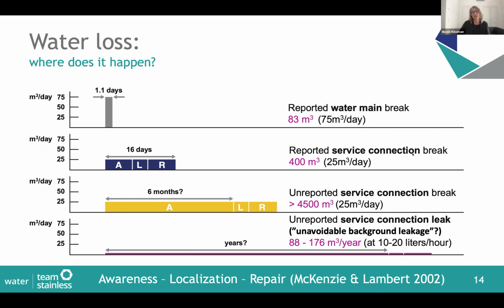But between awareness that there is a leak, and then the finding of the leak, the localization, and then the repairing of the leak, several days may pass, maybe more than 2 weeks. So during these 16 days, we can say 20 days, we can say 10 days, but we say 16 days, it's about 400 cubic meters of water that's lost. So a lot more than in a water main break. But what about the unreported service connection breaks? Those that don't come to the surface may go on for months. So I gave an example here of maybe 6 months. That could be more than 4,500 cubic meters from a relatively small service connection.